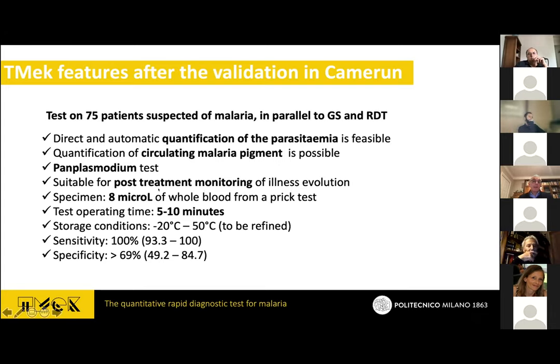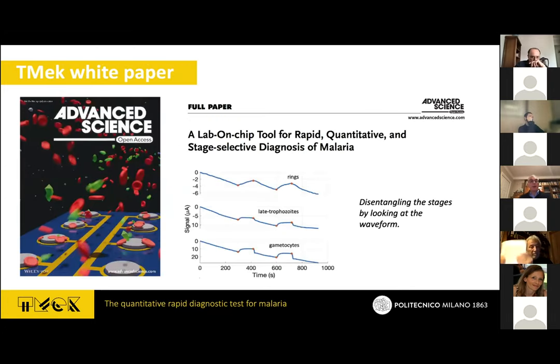And it can be used for post-treatment. We need just 8 microliter of whole blood, which means it's compatible with a prick test. And the operation time is 5-10 minutes. And the other point that is interesting is that you don't need reagents. So the storage conditions are really not a problem. You can really move to 50 Celsius degrees. And as a matter of fact, we have been operating at 40 degrees at that time. And sensitivity and specificity are those I discussed before. But, okay, this is the white paper that we published.